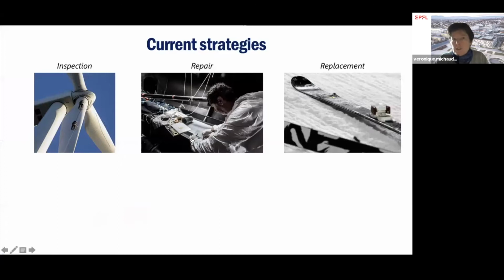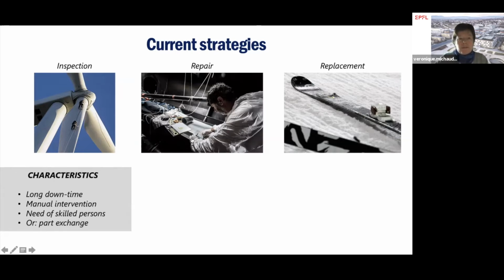So what are the current strategies when you have a composite failure that you would try to avoid? Well, of course, the strategy is to inspect or monitor, for example, a windmill blade every so often by sending people there. And then when you see that there has been damage using, for example, ultrasonic techniques, you can repair, which takes a lot of time, or you can actually throw away if it's a pair of skis and it's beyond repair. Of course, this all creates long downtimes, necessitates manual intervention, and is very costly, and needs also very skilled labor.